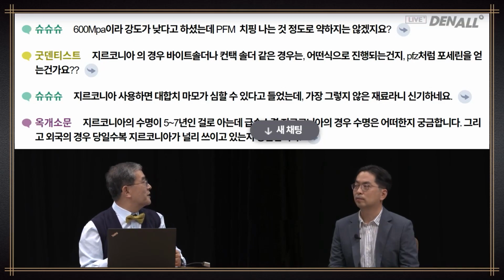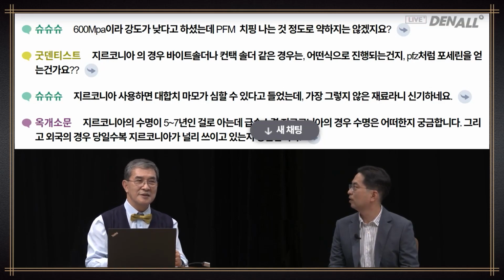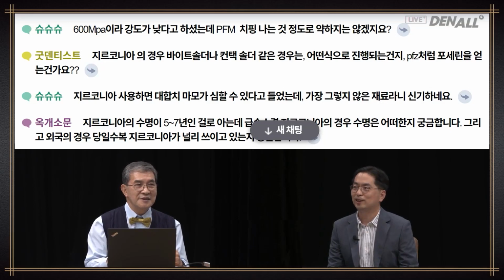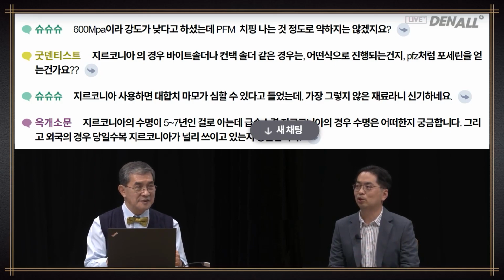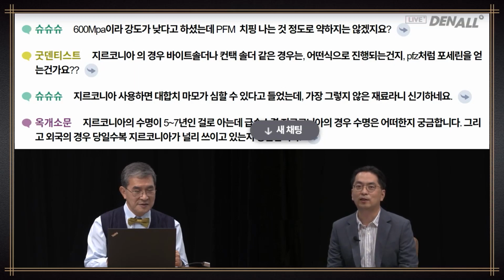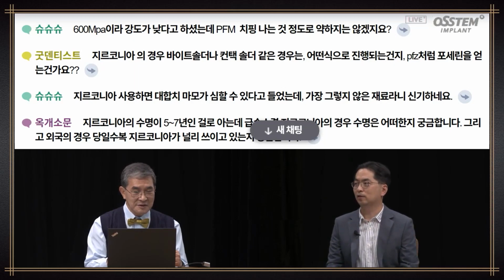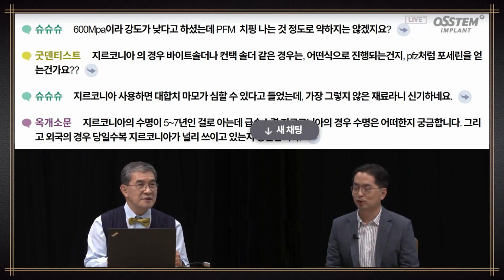We'll entertain up to Shu's question and then answer the rest after Dr. Lee's lecture. You said 600 megapascal. The strength is low, but is it so much so as PFM chipping? Chipping does not occur in zirconia. Fracture occurs, so the failure tendency is different. The PFM has a metal coping, so it does not have fracture, but in the case of zirconia, fracture occurs. If it is 600 megapascal, what's it like compared with a PFM? In the anterior area, you can use it, but I think it's quite dangerous to use it in the posterior area.